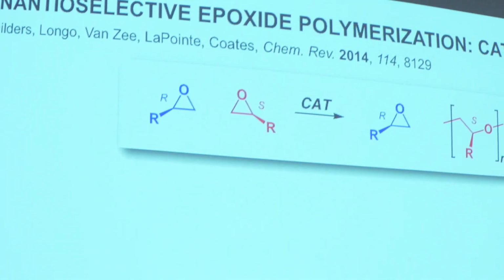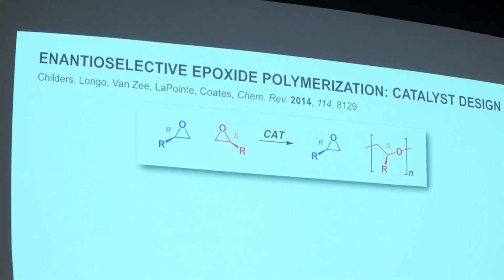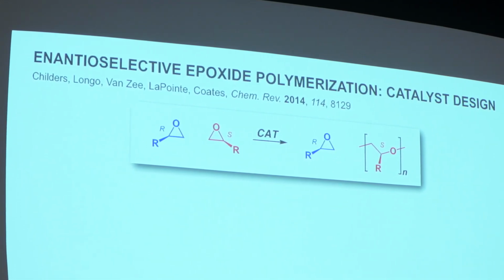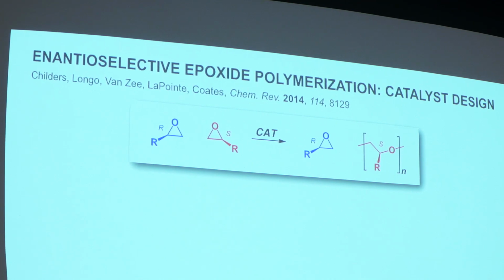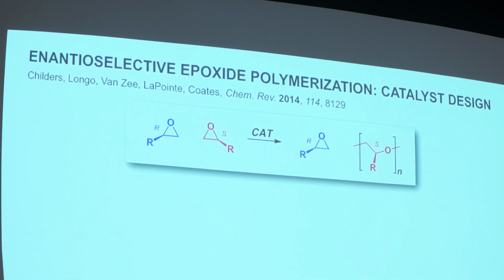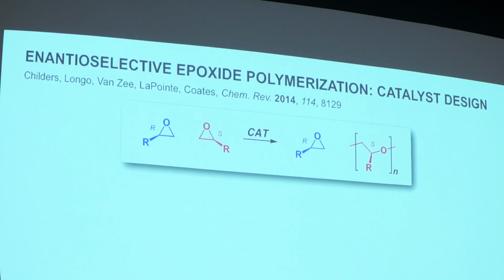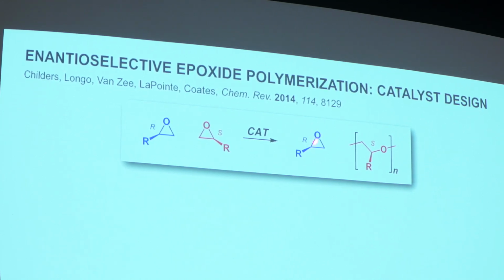And we thought maybe if you could come up with a higher value use of the unwanted enantiomer, then you could actually make this a lot more economical. And so what we decided to look at is a polymerization strategy. If you can take the racemic epoxide and develop a catalyst where the S enantiomer polymerizes, you're left with the R. The cool thing here is that this is a new-to-the-world polymer, but we've made some, and we know that it has properties that are almost as good as nylon. And so instead of throwing that away, we'd have a very valuable byproduct that might even be more valuable than the optically active epoxide that's left over.